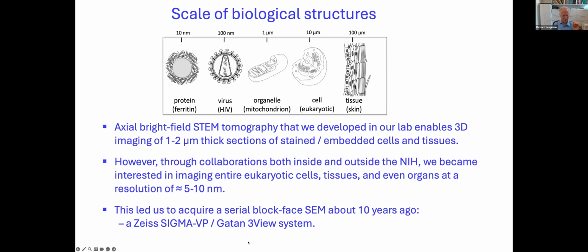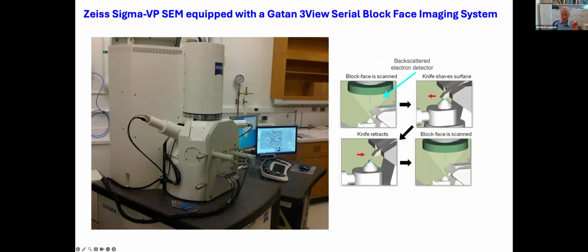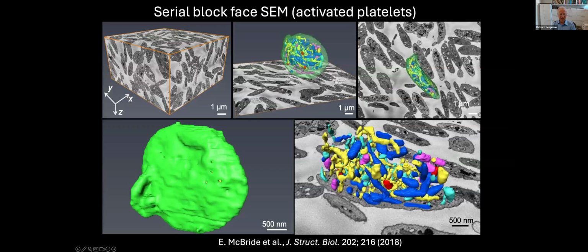We started with a Zeiss Sigma instrument, which had a Gatan 3View system, which was the microtome that was in the specimen stage of the microscope. And that's the picture of the instrument there. You can see the microtome inside the column, and a section is cut off the block, which is situated as shown, and the beam is subsequently scanned, the backscatter detector collects a signal from the specimen, and then that's repeated until you get a whole volume. So now you can see in these activated platelets the whole volume.